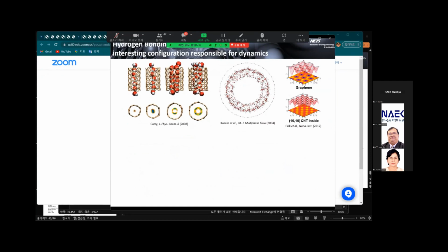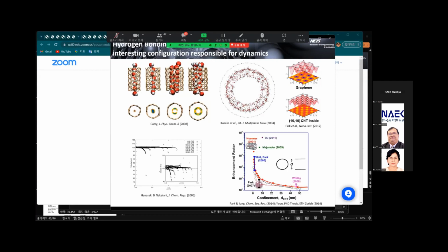For 1-nanometer-ish carbon nanotube channels, it is the chains of water molecules that run along in parallel, whereas for large carbon nanotube channels, it is the water layers right at the interface of water and the graphitic wall that carry the bulk water confined within them, resulting in plug-flow-like velocity profiles. However, when it comes to the question, how fast is fast, data from both simulations and experiments are not entirely aligned.